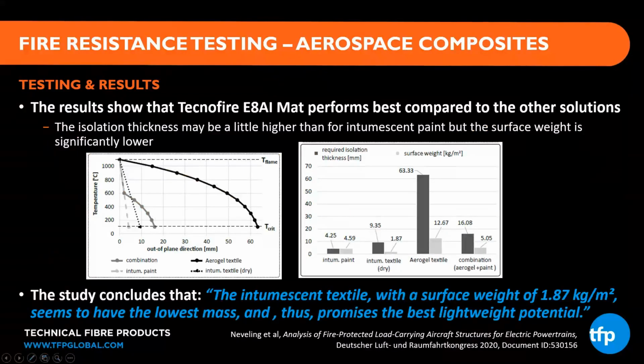So what they concluded, or what they found from the results, if you're looking at that graph on the left, the x-axis, you'll see a dotted line above that running horizontally. That is that 80 C critical temperature range. And the second line from the left, the dotted line that runs vertically at a slight angle, was the Tecnofire result. Now, if you look at the chart on the right, it breaks down the 4 materials. It's listed by the isolation thickness and also the surface weight.